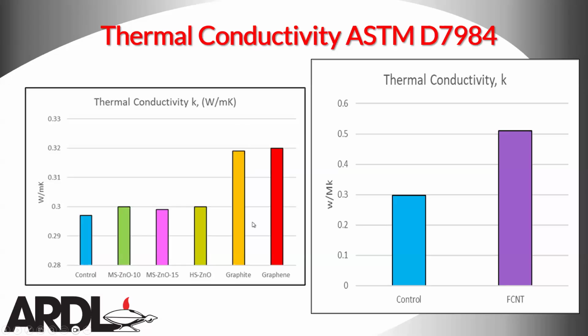And then you do also see higher thermal conductivity with the graphite and the graphene. The graphite one makes sense because we saw it had better aging, and we know that the poor dispersion is probably what caused the poor abrasion resistance. But you're still seeing high thermal conductivity from the graphene, and you were seeing good dispersion properties. So if I had to guess why the graphene did not give us better abrasion resistance, we did not use a functionalized or a treated graphene. And graphene in and of itself does not have high surface activity, so it's not going to give good polymer filler interaction. So what that means is that it's incorporated in the compound, but I don't necessarily think it is built up into the polymer backbone and reinforcing the compound.